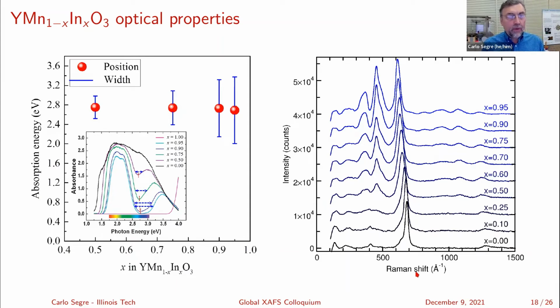I can't give you an exact answer on how big, and this addresses what Matthew was asking as well: at what point is it going to be necessary to say, well, there's an average structure? My guess is, if you heard Shoham's talk, he talked about a different system where he was looking at how quickly the structure relaxes from the local chemistry to a bulk value. And it's about the third shell, about the third near neighbor, where you get a structure that relaxes. So my guess, and this is just pure speculation because I don't know, is that these domains are probably only a few unit cells in size.